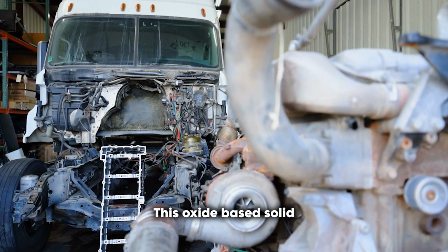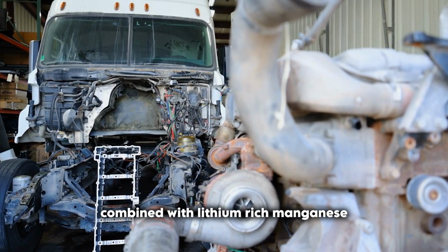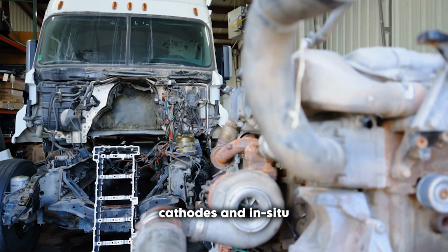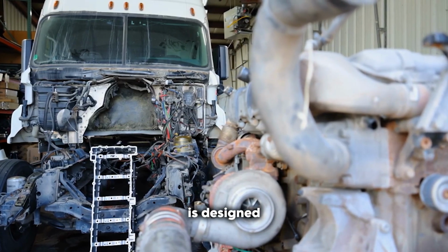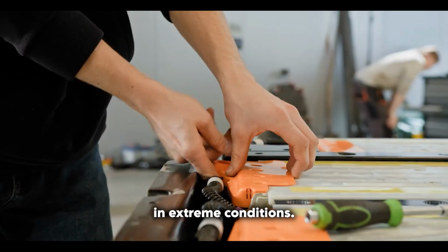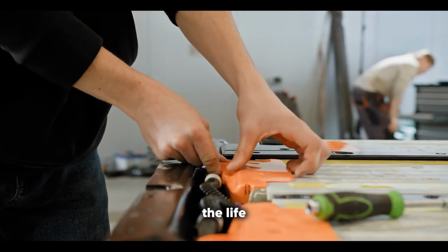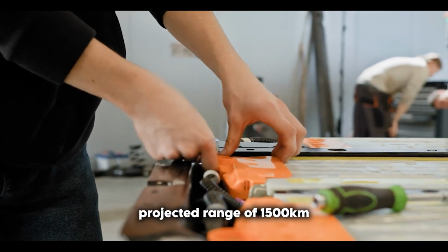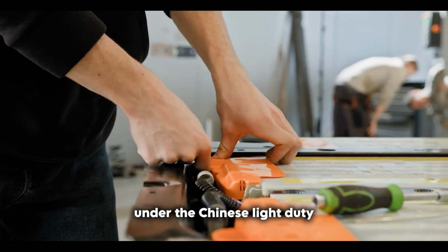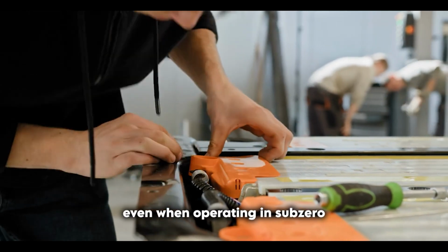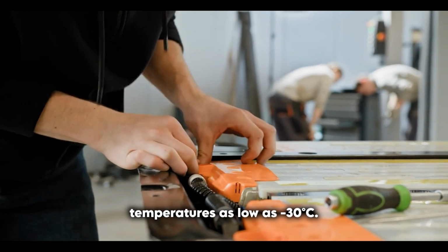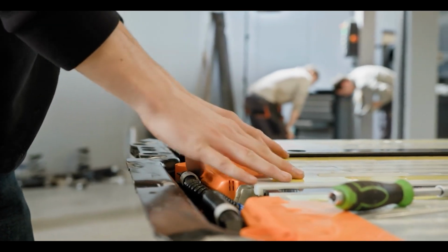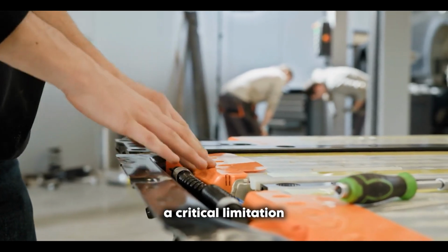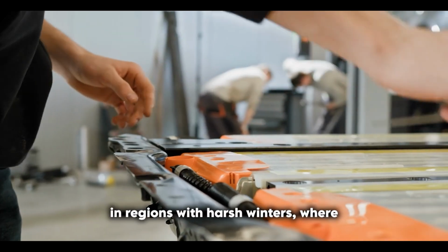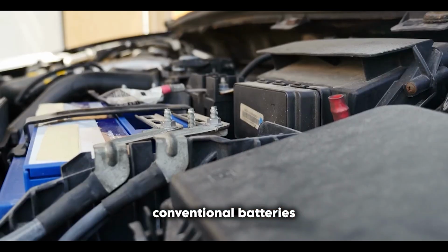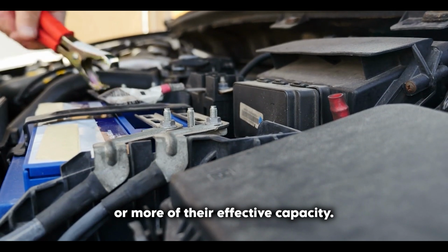This oxide-based solid electrolyte approach, combined with lithium-rich manganese cathodes and in-situ polymerization techniques, is designed to deliver outstanding performance in extreme conditions. Chery highlights the Lithing's projected range of 1,500 kilometers under the Chinese light-duty vehicle test cycle, even when operating in sub-zero temperatures as low as -30 degrees Celsius. This cold-weather prowess addresses a critical limitation for electric vehicles in regions with harsh winters, where conventional batteries can lose 40% or more of their effective capacity.